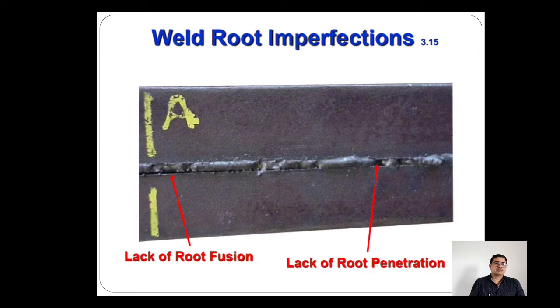So friends, in this I am going to start with the weld root imperfection. In the very left side you can see the lack of root fusion. Lack of root fusion shows in this figure that one side of the parent metal is not properly fused with the weld metal. However, on the right side of this picture you can see the weld metal has not completely fused or filled both sides of the parent metal.